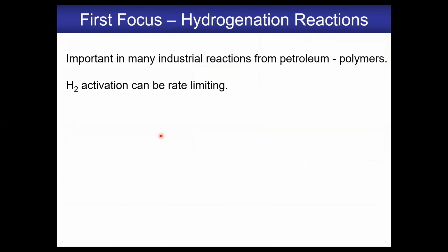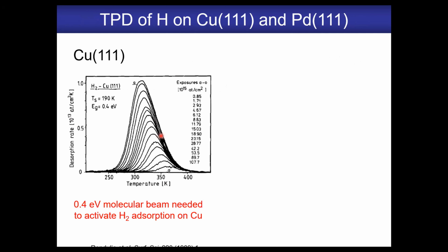Now to talk about the first class of reactions, hydrogenation reactions, because you quite often want to be selective in these reactions, you don't want to run your catalyst too hot in temperature. And in that case, hydrogen activation can be rate limiting. So let's talk about the energetics of hydrogen dissociation on pure copper and pure palladium, and then look at the mix. So on pure copper, hydrogen will not dissociate in a vacuum. You actually need a molecular beam to bring the hydrogen molecules in with higher energy in order for them to dissociate on the surface. But once you do, they'll recombine and desorb with regular second order kinetics.